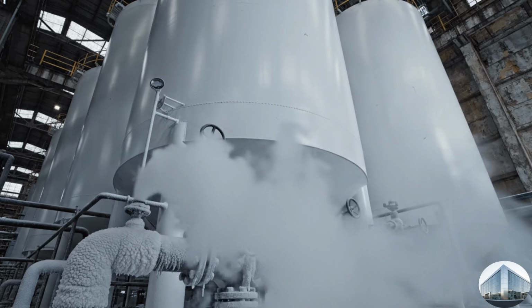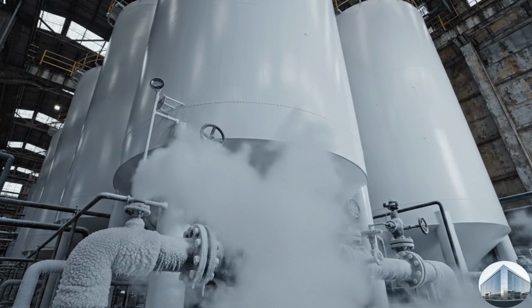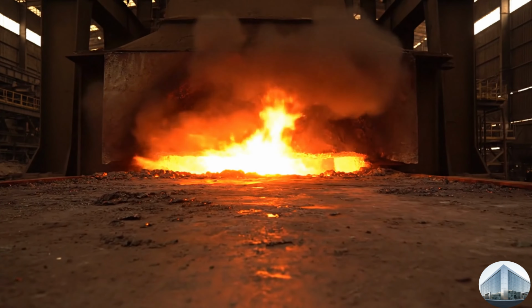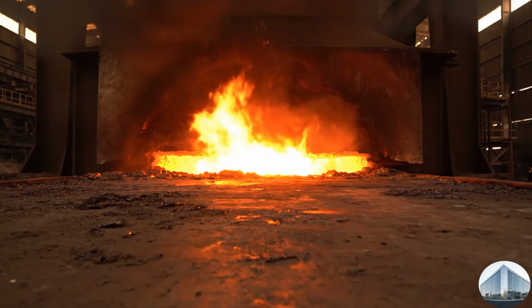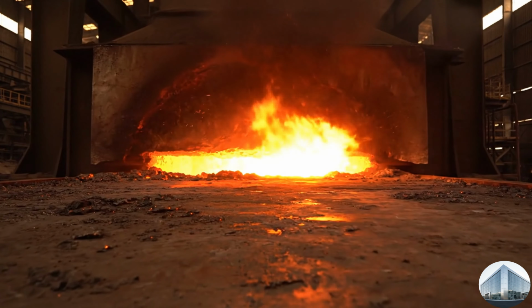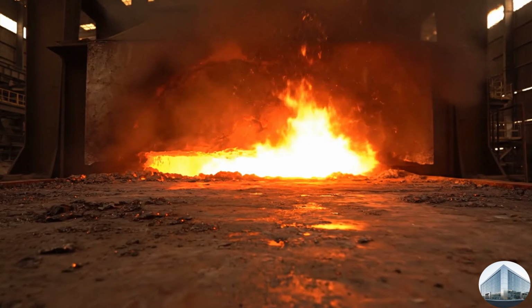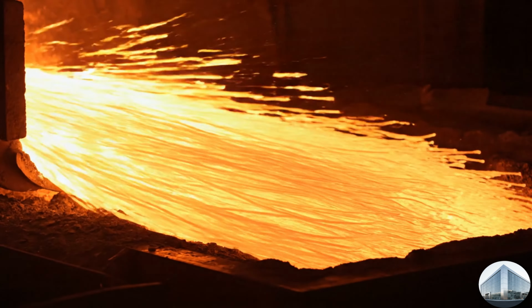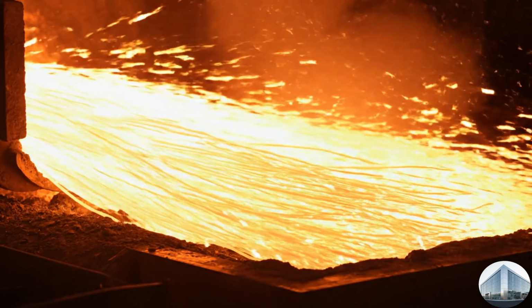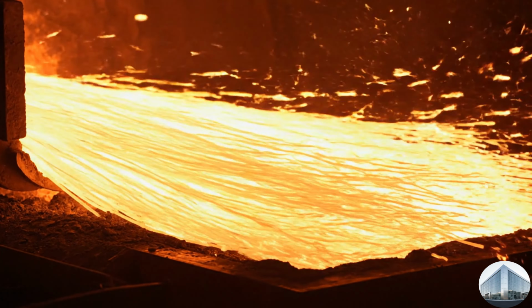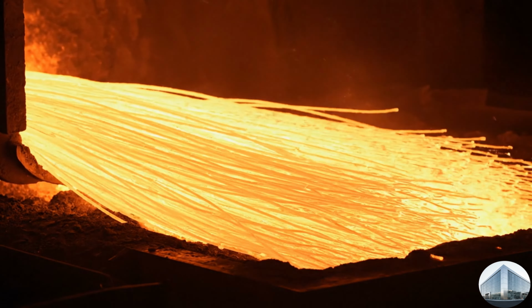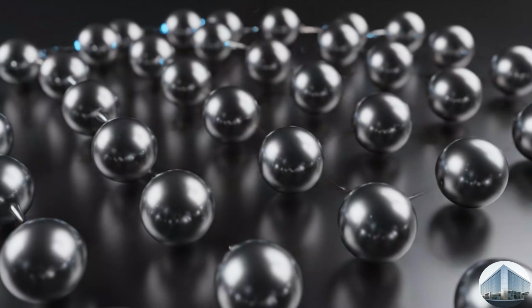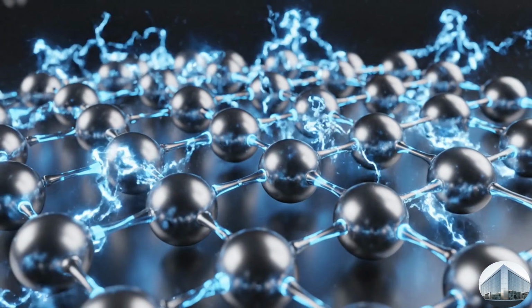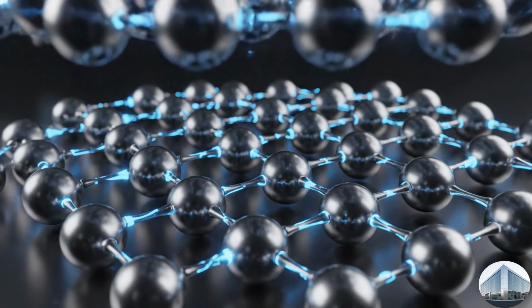Massive tanks of pure nitrogen provide an inert atmosphere, preventing the fibers from burning up in the extreme heat. Enter the carbonization stage. In this oxygen-free environment, the fibers are subjected to temperatures exceeding 1000 degrees Celsius, driving out all non-carbon atoms from the structure. Under this incredible heat, the material is purified. Hydrogen, nitrogen, and oxygen are expelled as gases, leaving behind a dense and incredibly strong network of pure carbon atoms.